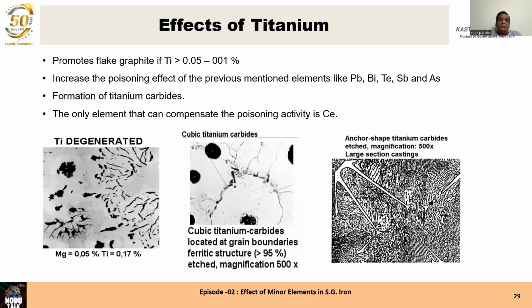Look at the effect of titanium degeneration of graphite in the figure on the left hand side. Hardly any graphite nodules, and the graphite nodules are all disturbed. They can hardly be called nodules. When titanium is present, at very high magnification you can see it forms cubic titanium carbides. These titanium carbides can be seen in the right hand side figure, and these are very hard carbides that cannot be removed by heat treatment. Titanium is a very dangerous element, especially when it is present with other subversive elements. It causes havoc in your SGI parts.